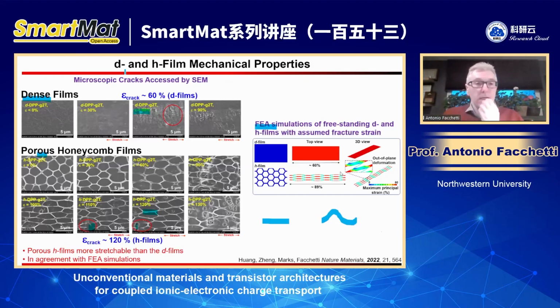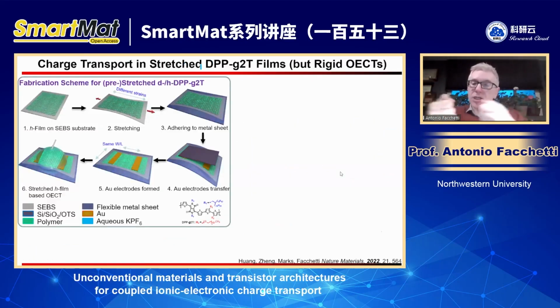Then we started making devices and started to understand the charge transport when you stretch the film. But we wanted to study the stretching independently of the contact deformation, okay? And in order to do that, what we did, we have fabricated the dense or honeycomb film on a substrate, then we stretch them at different degrees, okay? Then we laminated the stretched semiconductor at different extents on top of the contacts, okay? Then we finish the device.